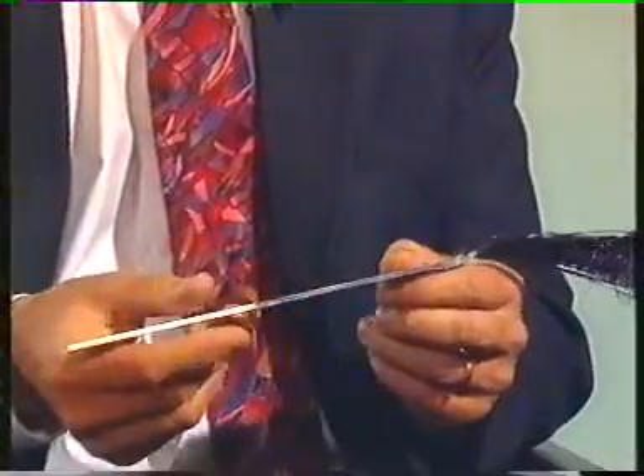This is a demonstration piece which actually consists of some ceramic fibres. These are silicon carbide ceramic fibres in a matrix which simulates the ceramic matrix. At this end there are no fibres, and in the middle there is a composite. As you can see, the fibres are floppy and don't retain a shape. The matrix on its own is brittle, as you can see.